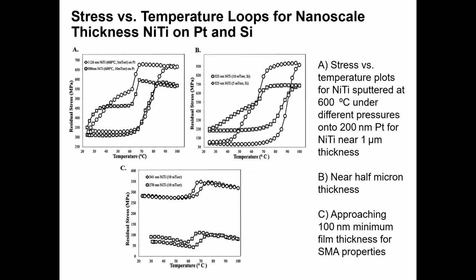So figures A and B are showing the thermal stress scans on the thicker films for which XRD showed significant volume fractions of the martensitic phase. And therefore these films had more significant changes in stress associated with this reversible phase change. Figure C shows 2 of the thinner NiTi films for which XRD still showed crystallization, but primarily austenite phase at room temperature. So a small amount of the film was able to undergo these thermal transformations. And therefore a hysteresis change was measured around 60 or 70 degrees, but this was at diminished values of recovery stress.